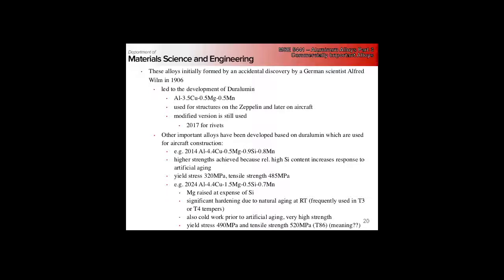The next generation after that of important aluminum alloys was completely based on duralumin, so 2014 and 2024. 2014 gives us—you add a little more silicon in there—so you get a better response to artificial aging because you get GP zones of both copper and silicon.